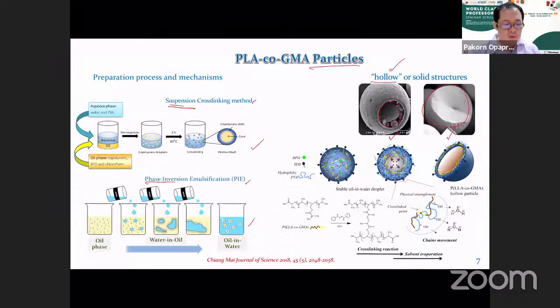And so we also investigate further into the mechanism of these two methods. So why can we get this different structure? We found out that the role of PVA that we employ as surfactant in this system, and also SDS, these two surfactants, along with solvent evaporation, play a key role in making hollow structure like this.